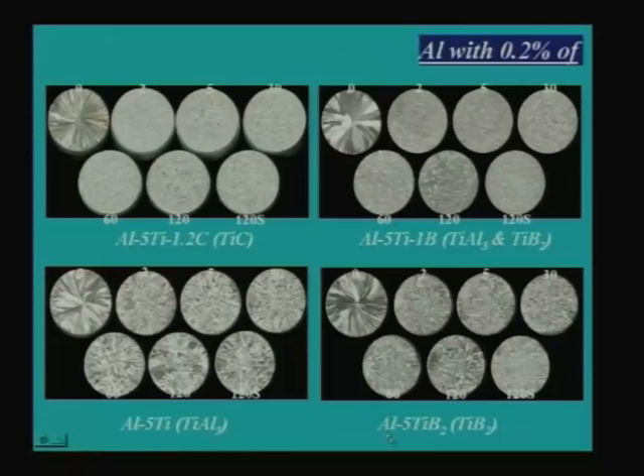You add aluminum 5 TiB2 composite where only TiB2 is there, again here also you get grain refinement but not as good grain refinement as you get with TiC alone. So, here you have only TiC. Here if you take aluminum 5 titanium 1 boron kind of master alloy, which is a conventional grain refiner, it will have both TiAl3 and TiB2. So, if you compare all this, this gives you an idea of the grain refining potency or grain refining efficiency of individual particles. How does TiAl3 act? That means, for example, whenever we are talking of heterogeneous nucleation, what is important is what is called contact angle.